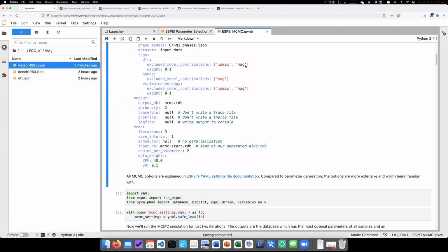But the problem is, and we have been struggling with that, is that when you have a phase and the reference states, for example, take something with iron or cobalt, the SER value actually corresponds to the paramagnetic state. So you really need to reduce everything for the non-magnetic Gibbs energy to the paramagnetic one. And you get the magnetic moment from the DFT calculations. The issue is the Curie temperature, because that is not a trivial issue to do with first principles.